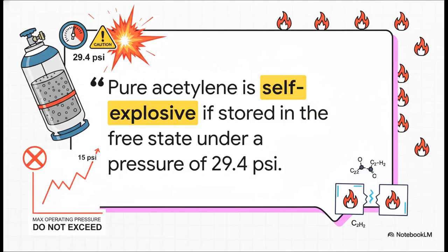And here are the hard numbers on that danger, straight from the source material. At just under 30 psi, free acetylene can decompose explosively without any spark or ignition source at all. So to give a massive safety factor and stay far, far away from that danger zone, the industry has a strict, non-negotiable rule. The absolute maximum working pressure for acetylene is 15 psi. That's not a guideline. It's a critical safety boundary that you have to respect on every single setup.